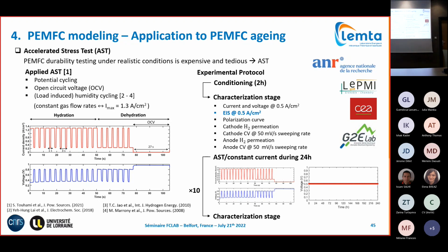So the thing that we can retain from this work is that you have a way to modelize the system, and you identify with the electrochemical spectroscopy the real values of the parameters of your electrical circuit, and you just tune these parameters so your model can reproduce this data. To be sure, we do not tune the parameters, we identify the parameters, because all our modeling is